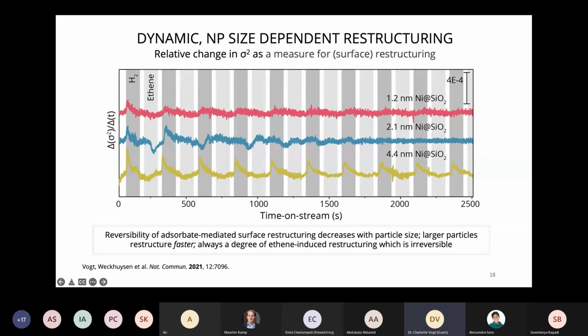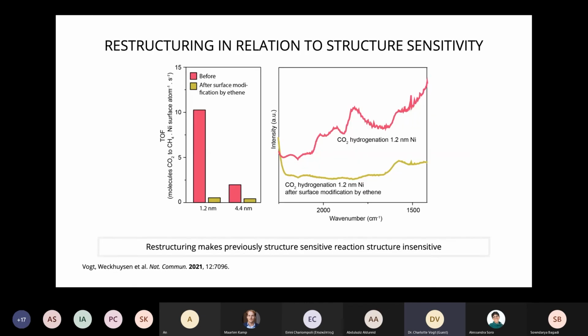couple with the observations that we had in our in situ high-resolution transmission electron microscopy because we observed grain boundaries on the larger nanoparticles. And in fact, carbon dissipates into grain boundaries approximately an order of magnitude faster than it does for clear surfaces. So coming back to this structure sensitivity, structure insensitivity question, if there is this thing which restructures the surface of nanoparticles so significantly, that might be the thing that is causing a certain amount of surface to be exposed.